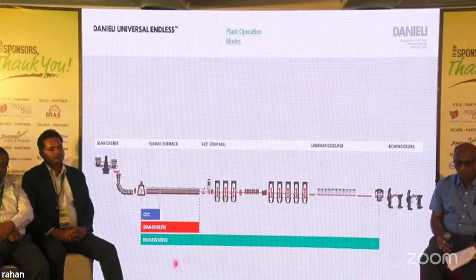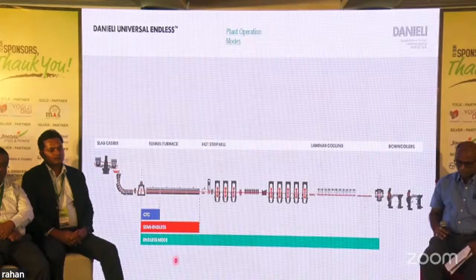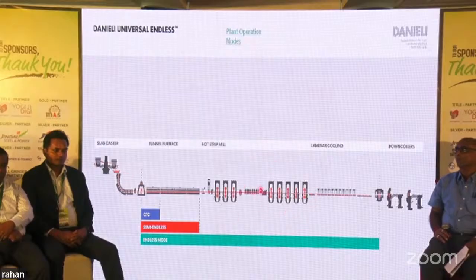Let me give you a point like semi-endless. When do you prefer a semi-endless? For instance, you would like to roll silicon steel or ultra low carbon steel, which has the limitations of having slow casting speed, but at the same time has to have a higher finishing mill exit temperature, which are contradicting statements. So you have a slow casting speed from the caster, but you need to have a higher temperature at the FM exit. So that's where these induction heaters in between will help you. And so a semi-endless will give you a better feature. Now I'll explain to you what these CTC, semi-endless and endless are.